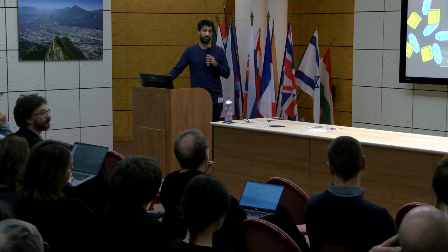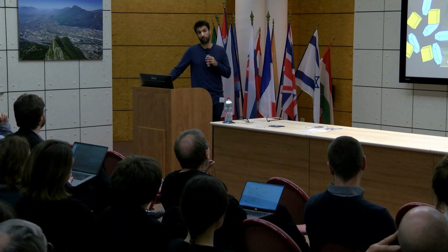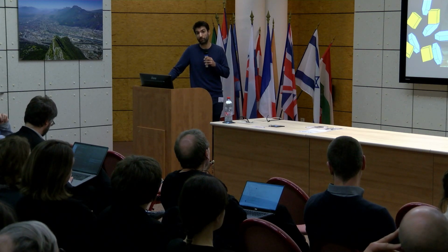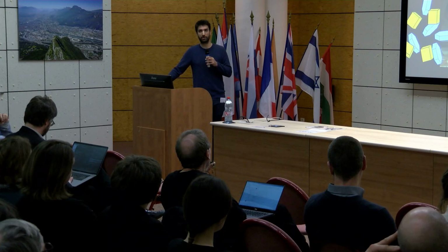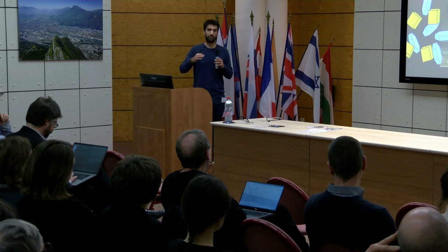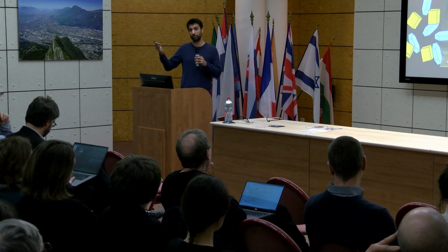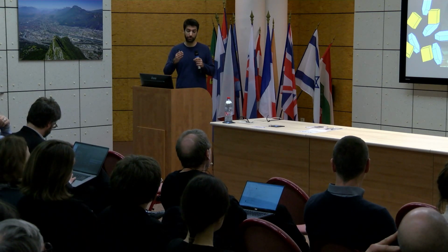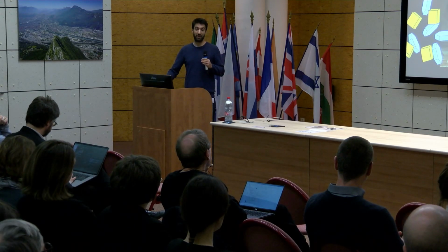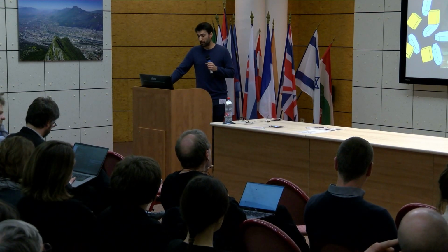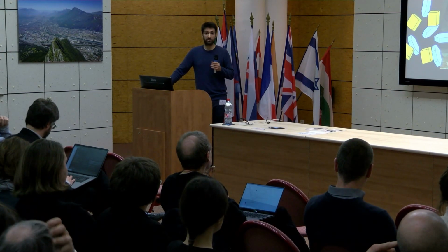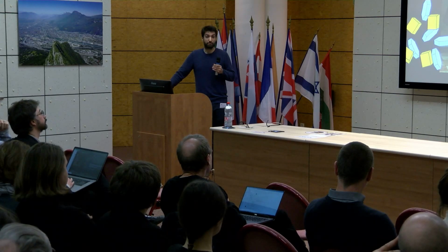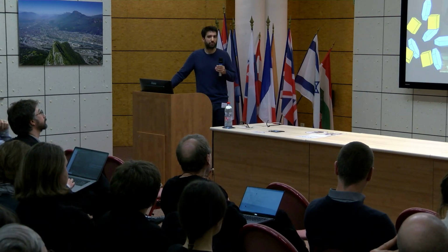That's absolutely indeed. This is a working hypothesis, but indeed, for example, in the case of impasto, there is now a new project being developed at the Rijksmuseum where it will be more focused on, for example, the morphologies of crystallites, and if this has something to do with the rheology. So there are different routes to approach this problem. Basically, the fact that plumbonacrite is present means that something is alkaline. So to us, this was the most obvious answer.